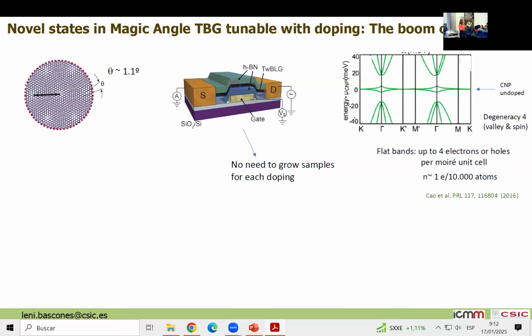What Pablo Jarillo-Herrero did was, now he had really a twisted bilayer. It was much more controlled. He had 2 layers of graphene really rotated around 1 degree. And already in 2016, he had put this twisted bilayer in a gate structure. The interesting thing here is that with these gates, he is able to dope the system.